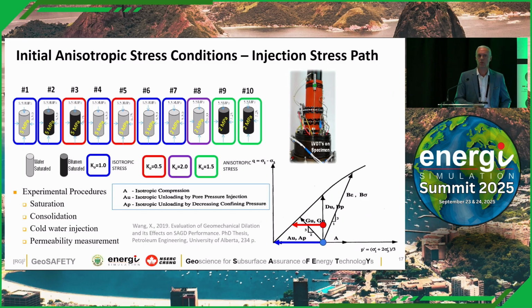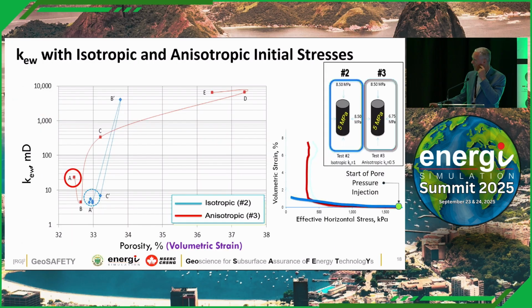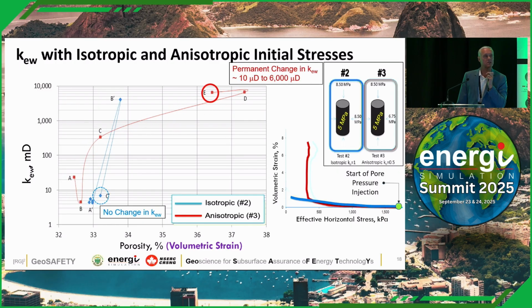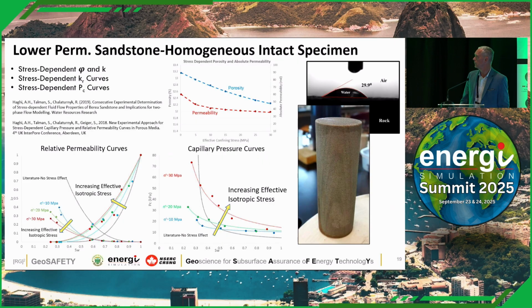What about pore pressure injection? What if all I had was an initial anisotropic in situ stress state and I injected pore pressure? What happens? This is a case where the samples were initially loaded to anisotropic stresses, and the path I'm going to follow is to move to the left from this red dot. So not down on this historical line down here, but from up here, what do I get? Well, if I'm isotropic, I get the blue. I go up. That's the normal pore volume compressibility that you have in all your simulators. I go up and I come back down. Not quite exactly that, but I get it. But if I'm under anisotropic in situ stresses, I get this. And that's quite substantial. I immediately get a substantially different volumetric behavior and a completely different pore pressure.